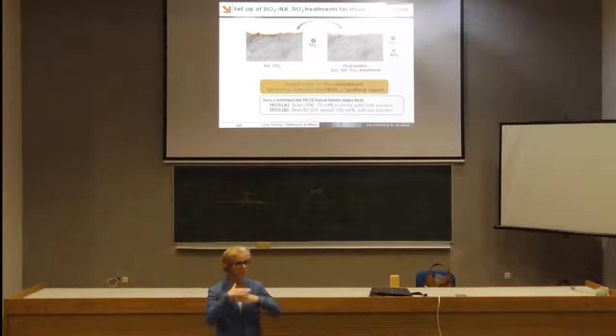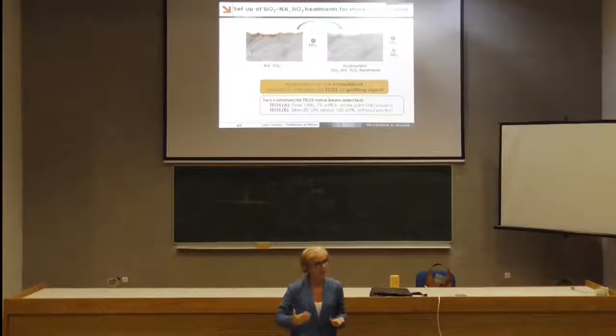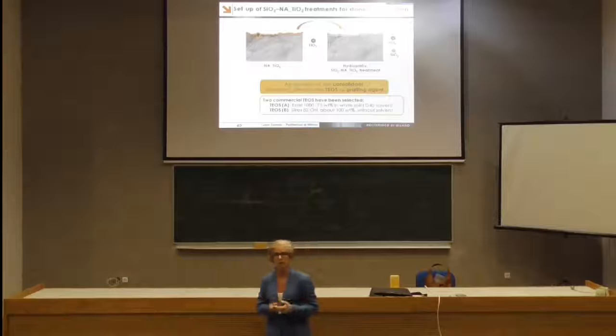So we have tried to perform a two-layer treatment that can have a consolidant effect on the substrate, and at the same time be self-cleaning. So the particulate matter doesn't accumulate on the surface, and the organic materials are oxidized.